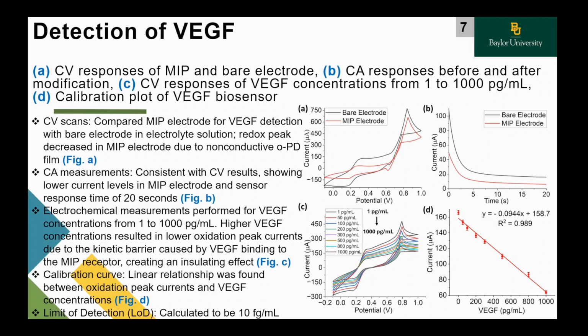The sensor characterization for VEGF detection is depicted here. The MIP electrode for VEGF detection was compared with bare electrode via CV scans in electrolyte solution, where the redox peak decreased in MIP electrode due to non-conductive OPD film. The CA measurement were consistent with CV result, showing lower current level in MIP electrode and sensor response time of 20 seconds. After that, the electrochemical measurement was performed for VEGF concentration from 1 to 1,000 picogram per milliliter.